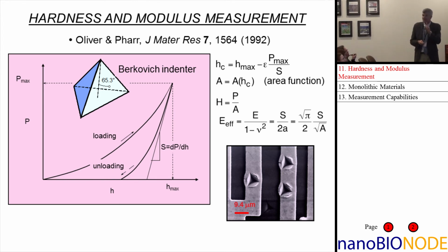And the 10% of the cases in which it doesn't work are the ones where the material has strong tendency to pile up, where things are very, very plastic. Then there's going to be a problem because you don't get the contact depth right. But the idea then is that if you know the depth along which contact is made, then you can get the area of contact by knowing the precise shape of the indenter. It comes from the geometry of the indenter, the known depth.